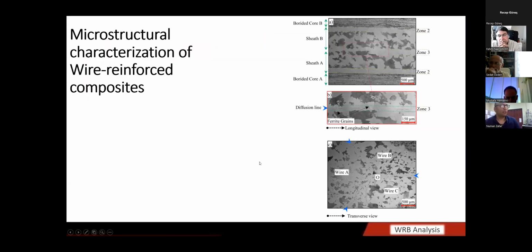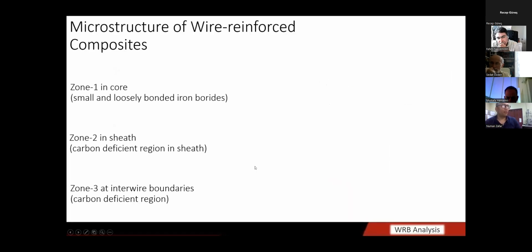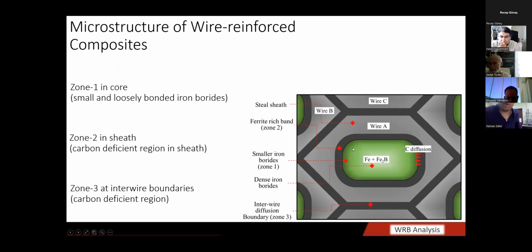That is called zone 1. Zone 3 is the region at interwire boundaries. There too, we can see these ferrite bands, with no pearlite structure. So they are carbon deficient regions. Here is a cross section of wires A, B, and C, and this O region is the place where they are bonded. I have divided the whole microstructure into 3 zones. Zone 1 is small and loosely bonded iron boride phases. Zone 2 in the sheath is a carbon deficient region, and zone 3 is also the interwire boundaries carbon deficient region. This is a summary of the microstructure. All features of the microstructure are given here.